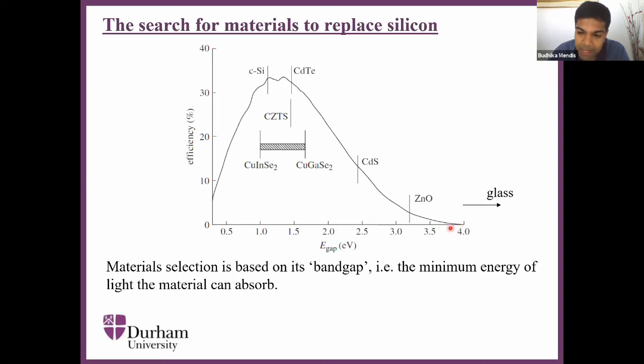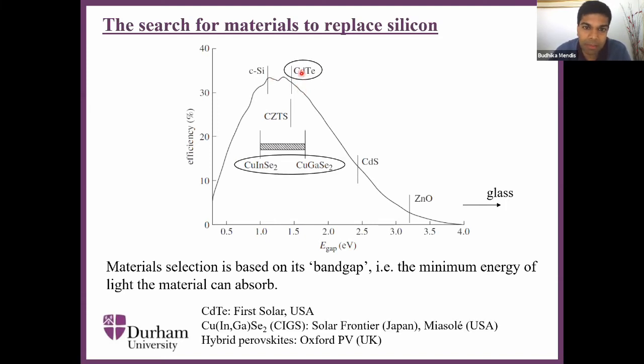However, if we reduce the band gap, so glass would sit to the right of this diagram, as we gradually reduce the band gap, then the efficiency starts increasing until we hit a sweet spot. So the first step in selecting materials is to find those materials which have band gap in this sweet spot region. And we come up with a number of contenders. So you have cadmium telluride, as well as compounds containing copper indium diselenide and copper gallium diselenide. These materials have actually been commercialized.